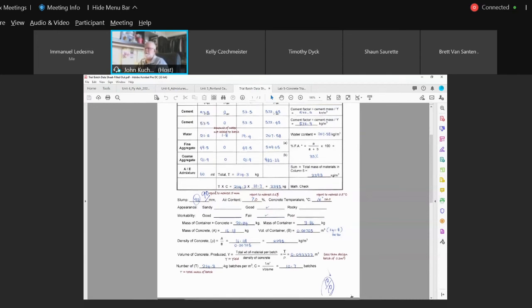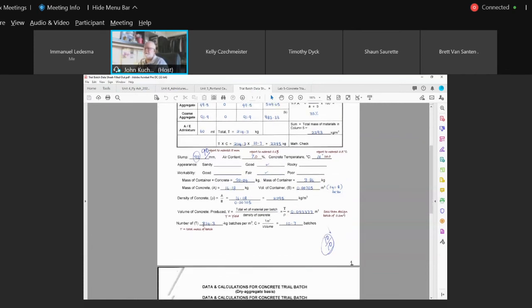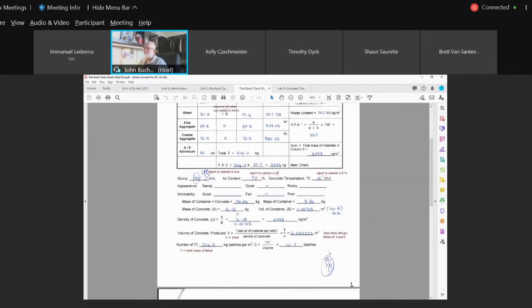Now, this is a batch. Each batch is 214.3 kilograms. So how many batches totaling 214.3 kgs were there in a cubic meter of concrete? Well, that's pretty straightforward - you've got 1 cubic meter of concrete, and you divide it by the volume, and you get 10.7 batches. So if you're saying there's 10.7 batches, as a check, 10.7 times the density should give you 2295 - that's just a check for a cubic meter of concrete.